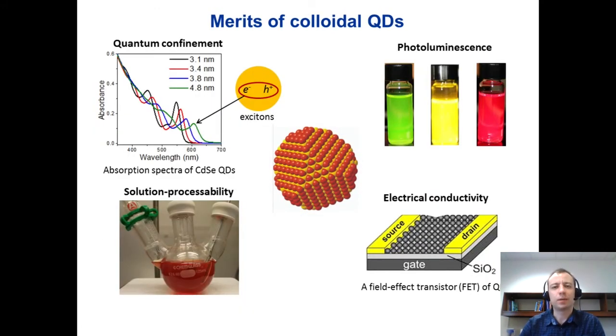So what's so special about these quantum dots? What are their merits? Well, first is quantum confinement. Unlike their parent bulk materials, the band gap of a quantum dot depends on its size. The smaller the quantum dot, the larger the band gap. Electron-hole pairs in these quantum dots form excitons, which manifest themselves as these peaks in absorption spectra. And we can see the smaller the quantum dot, the bluer it is.